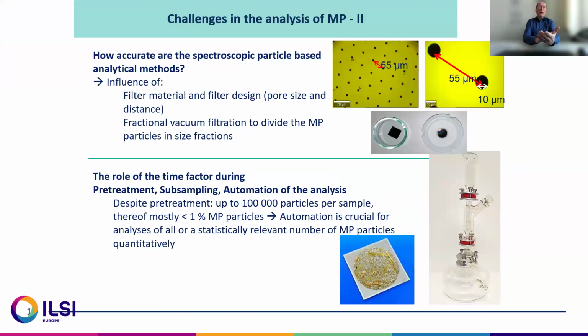Then the second point, what are challenges in the analysis, is how accurate are the spectroscopic particle-based analytical methods. Here we have an influence of the filter material. You can use Anodisc, silicon filters, gold filters, and so on. And very important is also the filter design. The pore size and the distance between the pores is shown here. And you should do a fractional vacuum filtration to divide the microplastic particles into size fractions, maybe below 5 microns, between 5 and 10, 10 and 20. Otherwise, bigger particles overlay smaller ones.